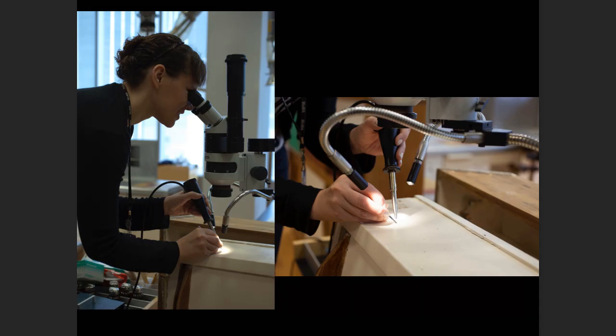Most of the overpaint on the doors and some of the sections we did discover was an acrylic paint. This was through our analysis and FTIR analysis. We know that was true. We knew then that this could be removed using heat and a scalpel. So it might have been an arduous task, but once you get into it, it actually goes